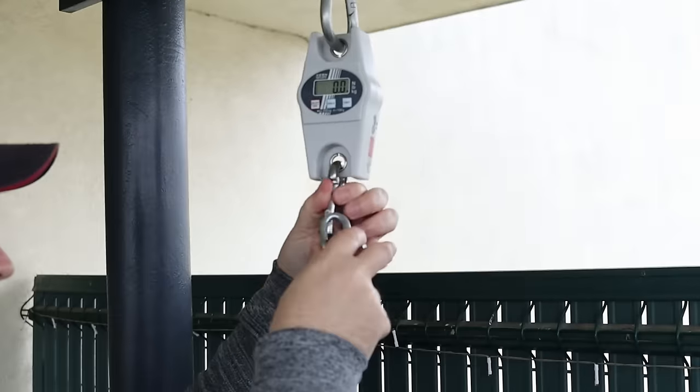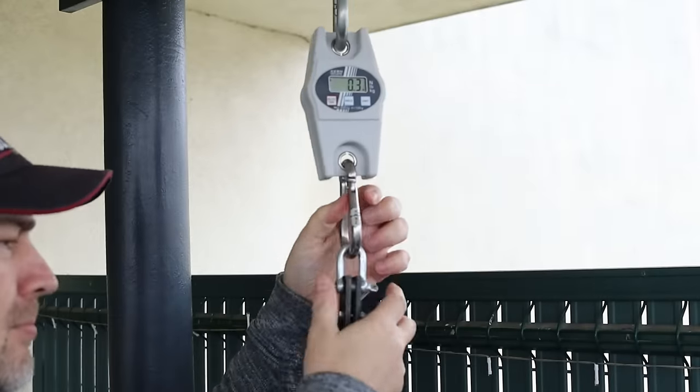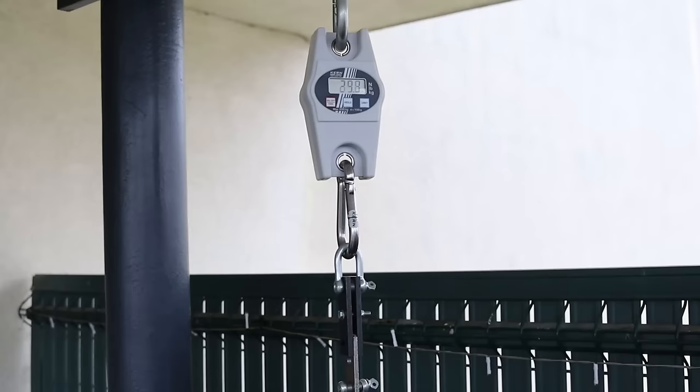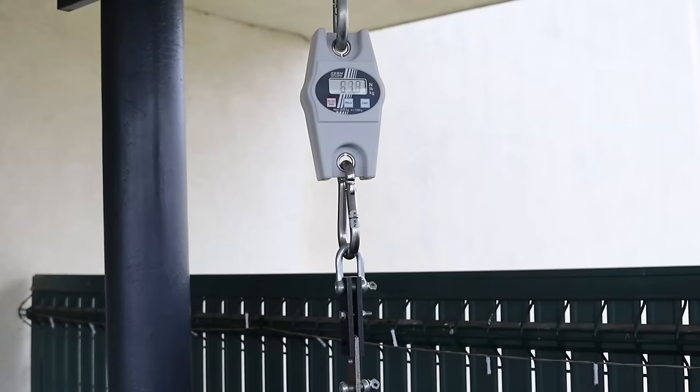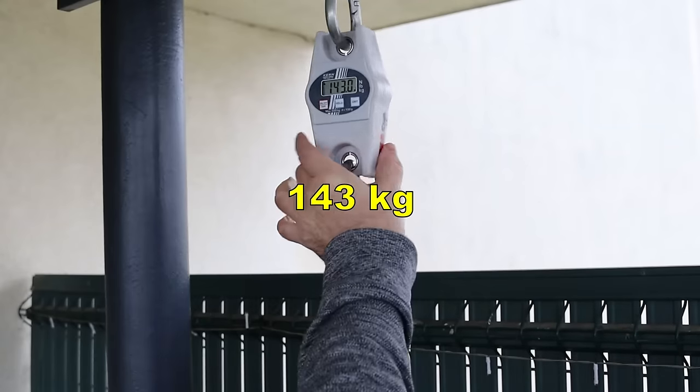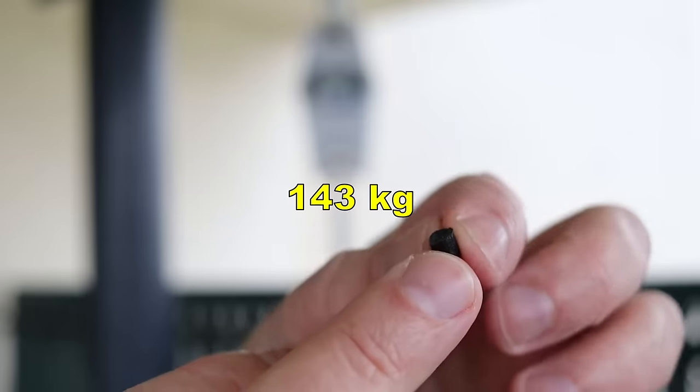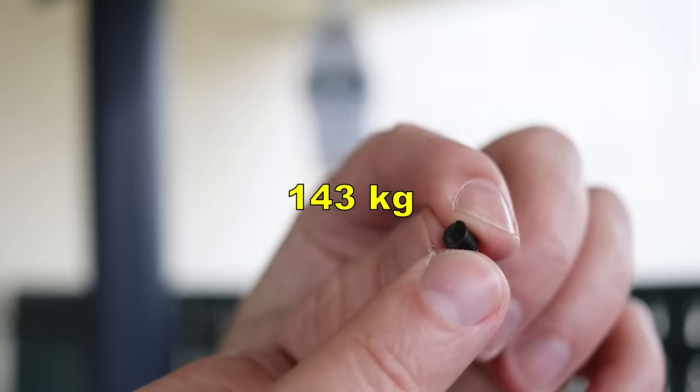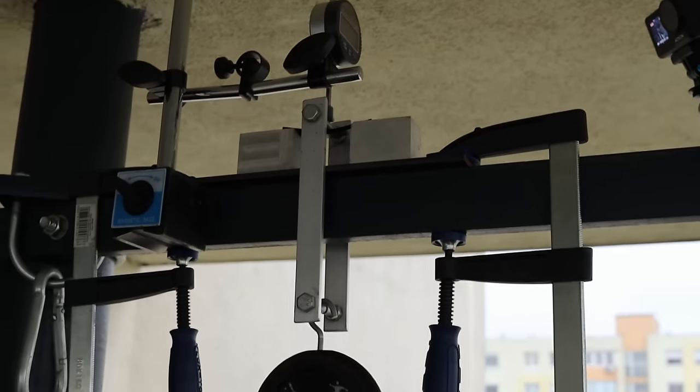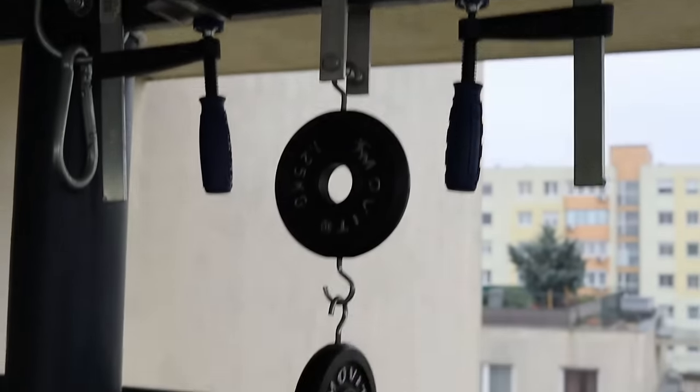Two-sided shear stress. The diameter of this test object is 5 millimeters. And a little bit stronger than average ABS. They sheared correctly but I couldn't find all three pieces.